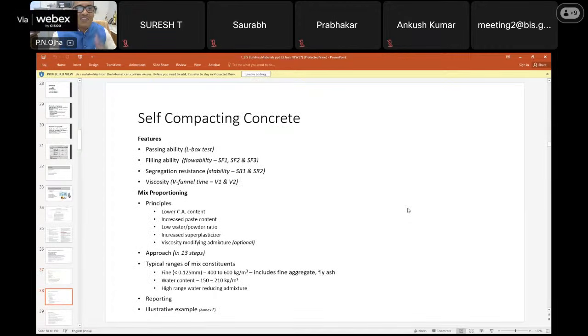Okay, and this is self-compacting concrete. So the features are passing ability, which is tested as per L-box, and there is a standard available in IS 1199, and filling ability, segregation resistance, and viscosity. So these are the four properties in the fresh concrete state for any self-compacting concrete. And according to this, when a self-compacting concrete is made, the trial is made after calculation following IS 10262, then these tests are done in the fresh state. When these are not meeting the specifications fixed by the user, then there should be adjustment in the concrete mix proportion. And how the mix proportioning should be done, the approach has been written in 13 steps. Okay, and one can follow.